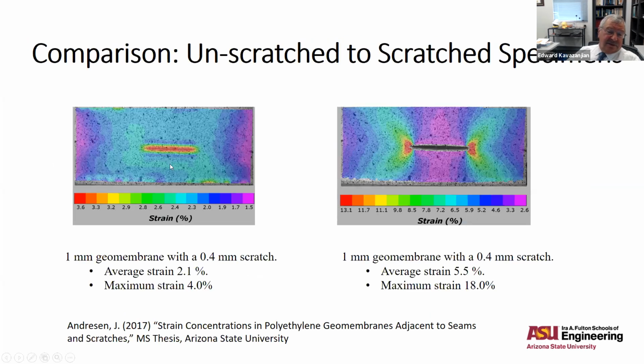And then there are scratches. So here are the DIC results for some intentional scratches we put in an unscratched geomembrane coupon. This is a 1 millimeter or 40 mil geomembrane with a scratch 0.4 millimeters deep, so 40% of the thickness. The average strain on the coupon was 2%. The maximum strain around the scratch was 4%.